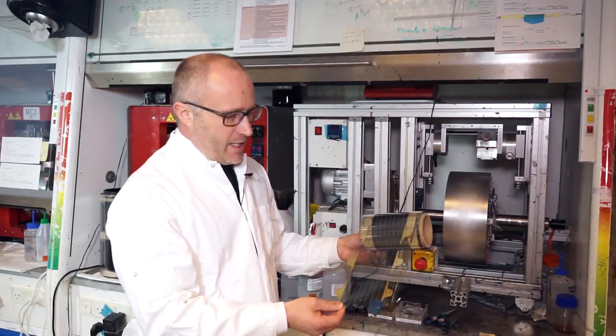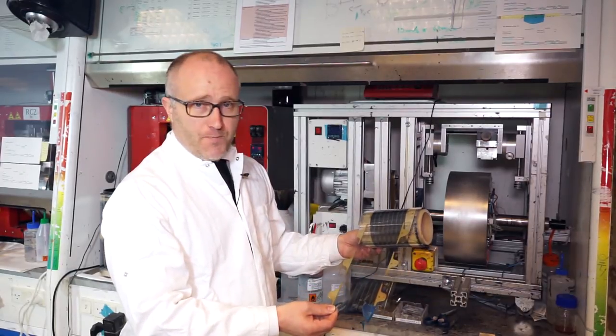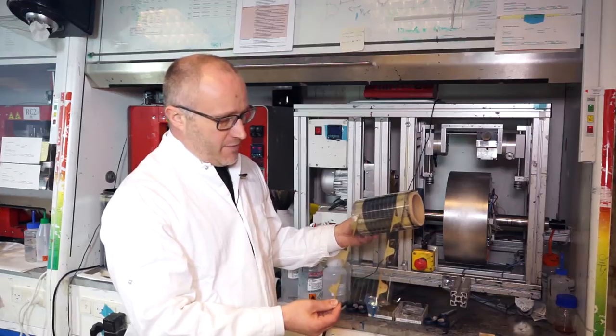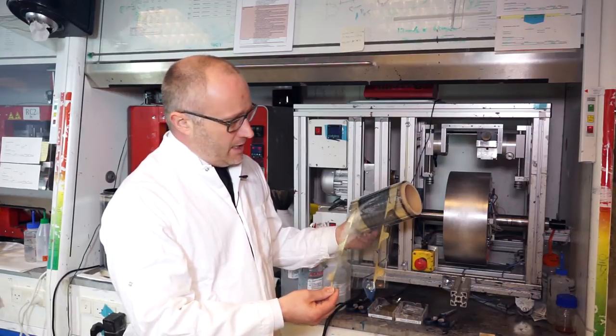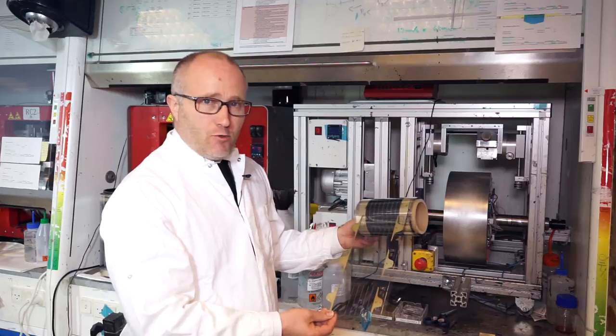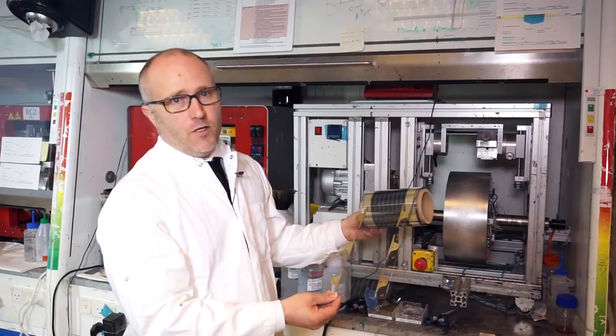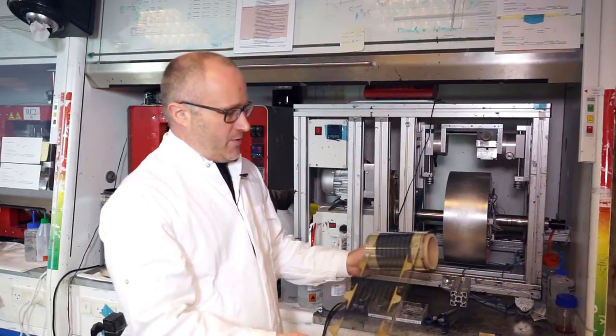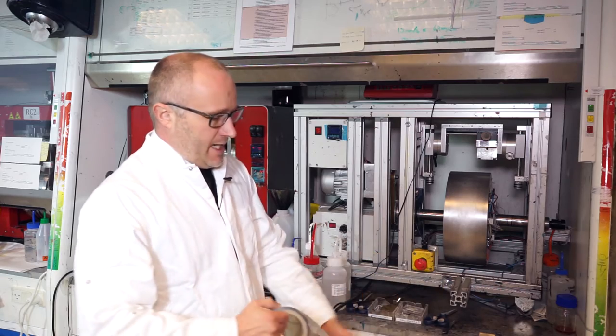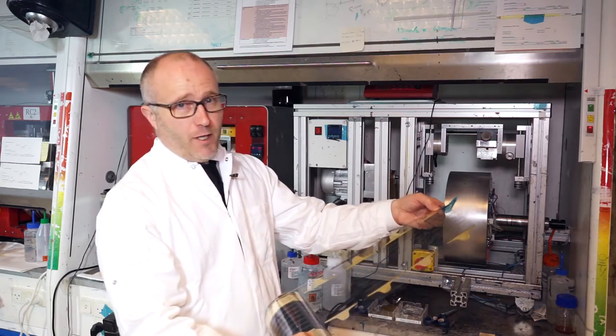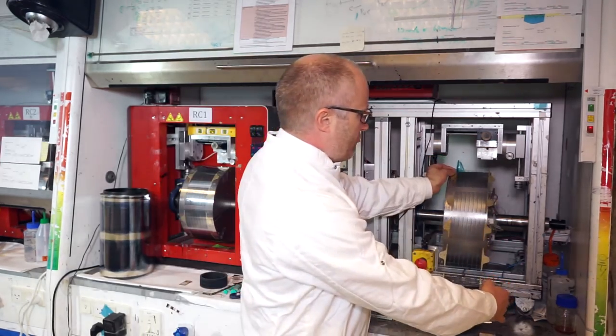So it's a complex two-dimensionally patterned electrode structure, has a flexo-printed silver grid, the rotary screen printed PEDOT, and in this case, a slot die coated zinc oxide layer. And this is for solar cells. And it's a semi-transparent conductor that you can then apply. You can cut off 1 meter, apply it to this roll.